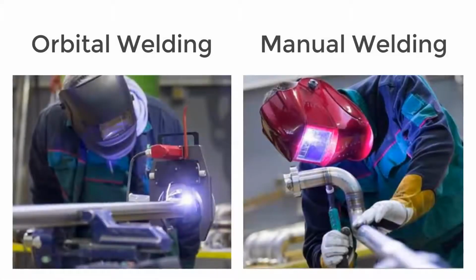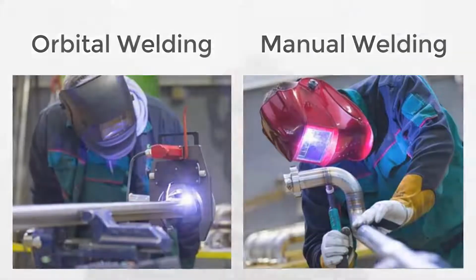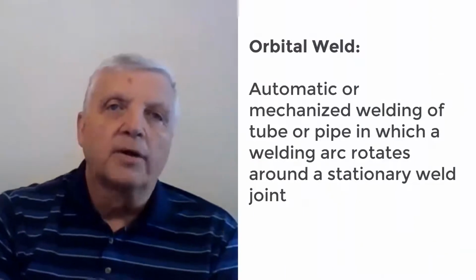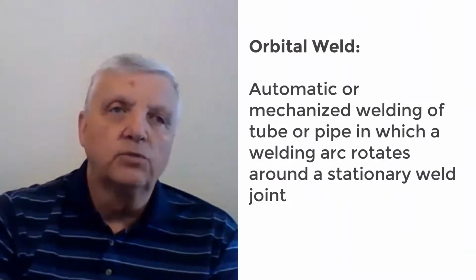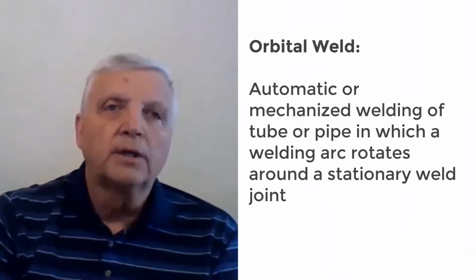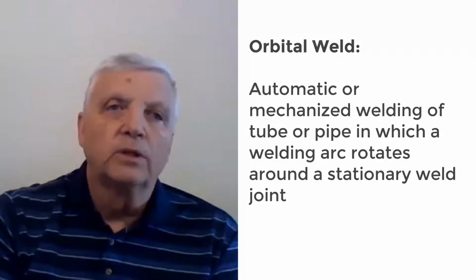Orbital welding is an automated machine welding process in comparison to manual welding. Orbital welding has almost exclusively been carried out by the tungsten inert gas technique, with and without the use of filler wire. AWS D18.1, which is the specification for welding of austenitic stainless steel tube and pipe systems in sanitary application, defines an orbital weld as automatic or mechanized welding of tube or pipe in which a welding arc rotates around a stationary weld joint.